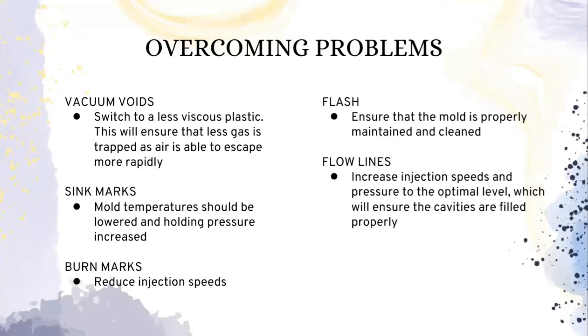Next is overcoming the problems. For the defect of vacuum void, we can switch to a less viscous plastic. This will ensure that less gas is trapped as air is able to escape more rapidly. For sink marks, mold temperatures should be lowered and holding pressure should be increased. For burn marks, we should reduce the injection speed.